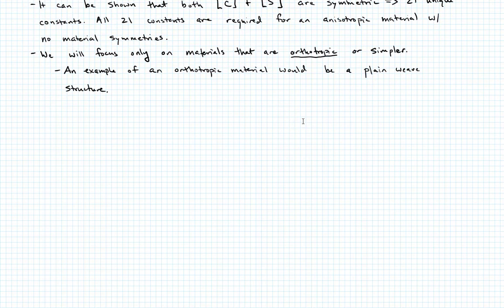So in the case of an orthotropic material, it can be defined with nine constants, essentially thinking about properties in each of three orthogonal directions. And those nine constants are going to be E1, E2, E3. These are just conventional stiffness values, effectively Young's moduli in the one, two, and three directions. Then the equivalent shear moduli, which would be G12, G13, and G23. And then similar for Poisson's ratios. So we have nu_12, nu_13, and nu_23. I will say that the coordinate system for these properties must be in the direction of material orthogonality. So think about if you have a plain weave, or maybe look at the grid on your paper, if those are the directions of the weave, then you need to align your axes in those directions to define these properties.